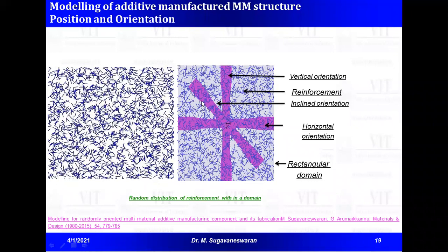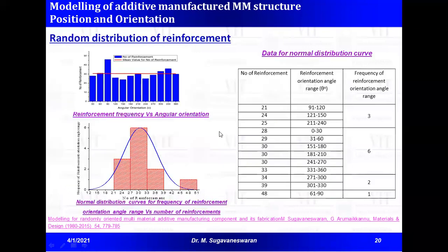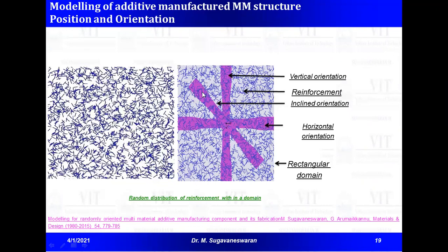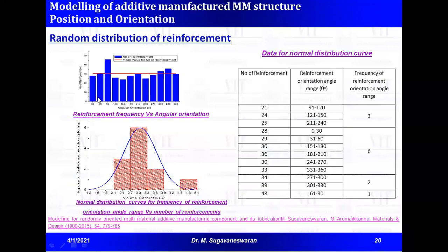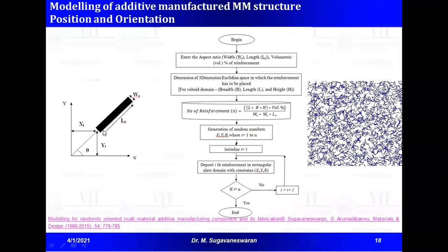Whatever we are going to develop in CAD will get replicated in printing, because as mentioned earlier, it is a pixel to print process. So to check the randomness of the distributed material, in three directions the specimen is taken out, in the CAD model itself, and these three samples alone are individually fabricated using a Stratasys PolyJet process, which supports multi-material printing. If we look into the distribution, here I have displayed the distribution of the reinforcement angle, because the randomness of the reinforcement is calculated based on the angle.